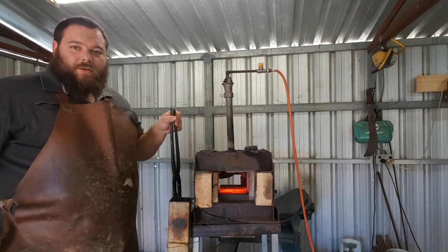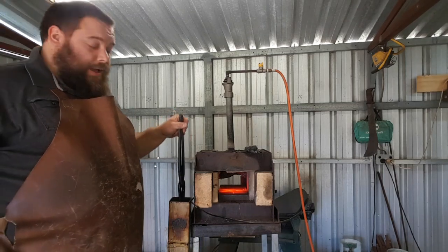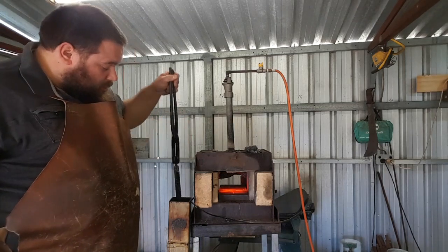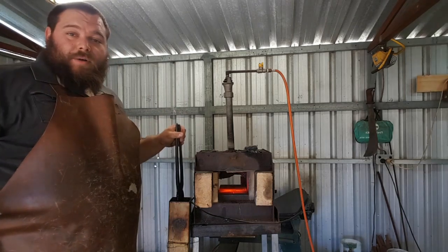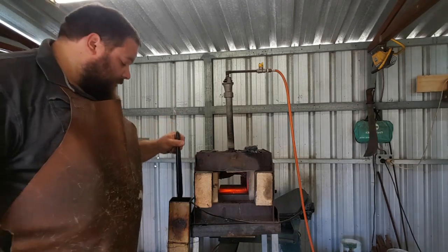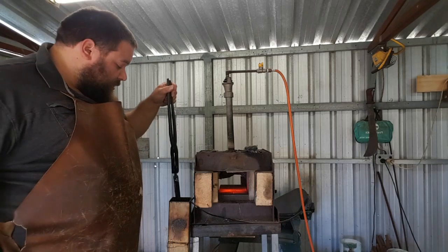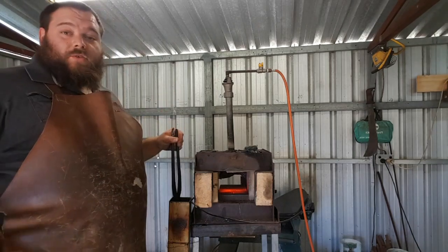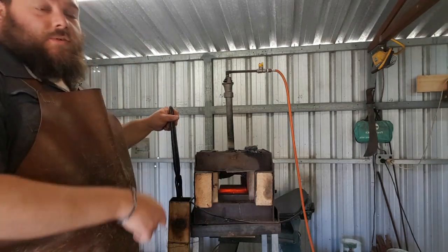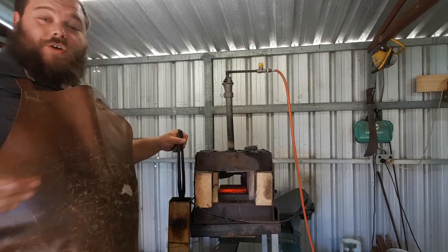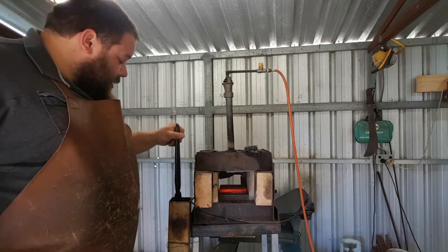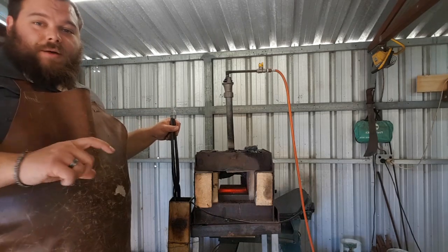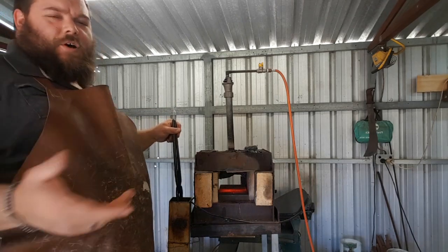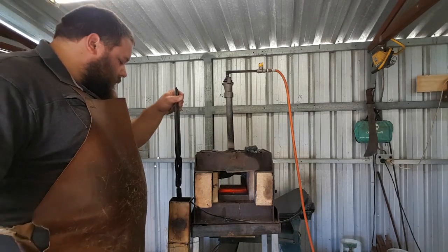The big thing is if you take too much time in going to the quench, you're going to end up with the outside or the thinner parts of your blade, the bevels and stuff like that, the tip, cooling down to normalization temperatures before you get to the quench. And if that happens, you don't end up with a hard blade. You end up with a hardened back and a soft edge, which is exactly the opposite of what you want.